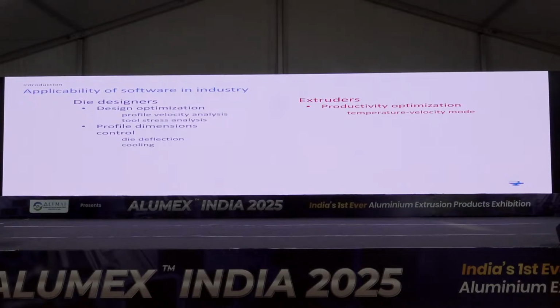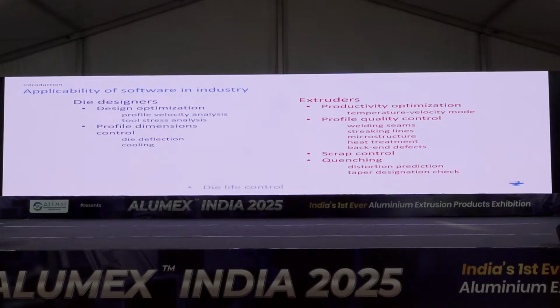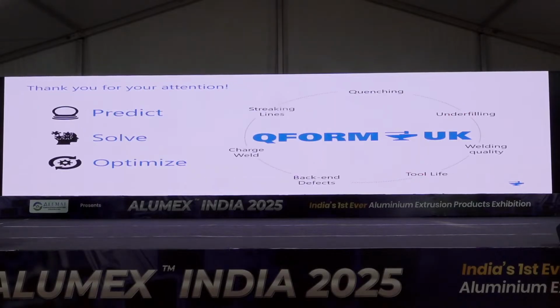Because if you find the limit of the extrusion speed using the simulation software, it's a good thing to know beforehand, before you start the extrusion. Profile quality control: all the defects that we discussed today can be predicted. Scrap control is very important. Quenching finally is available. And for both sides, die life control and charge weld control are very important. So basically that's it. This is what I wanted to show you concerning the simulation capabilities that we currently have. So we can start from scratch, create the design, and end up with an analysis of the quenched and cooled section. Thank you for your time.